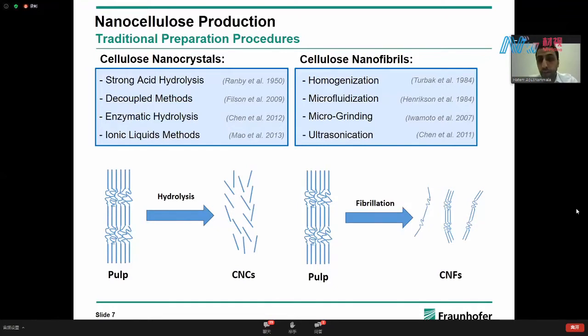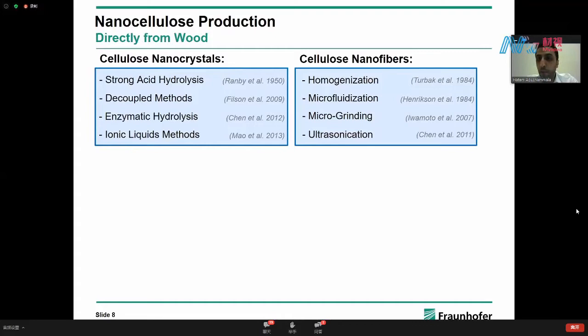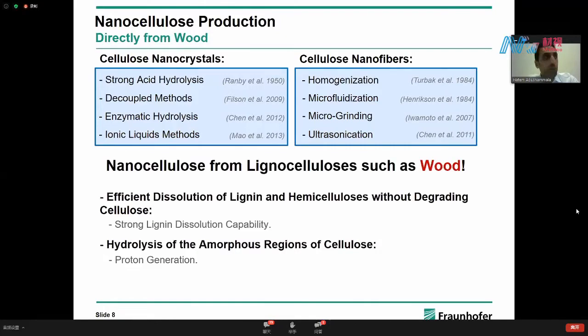One observation here, if you can notice, is that nanocellulose is mainly made from pure or almost pure sources of cellulose. And since I mentioned that there is great potential in lignocellulosic residues, what if we could make nanocellulose directly from wood and directly from lignocellulose? Because sometimes, for some of these residues, there is no point in pulping them. This was part of work I did around 5 years ago. It was not really surprising for us that there's no such process to make nanocellulose directly from wood and lignocellulose, because it's not easy to find an agent that can dissolve lignin, dissolve hemicelluloses, and also selectively dissolve the amorphous regions of cellulose without destroying the cellulosic crystallites.